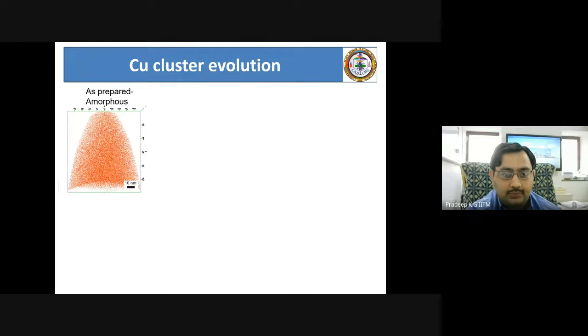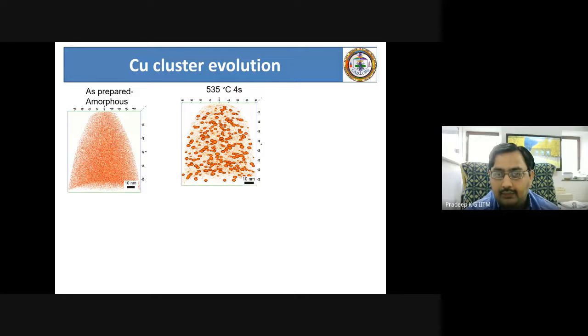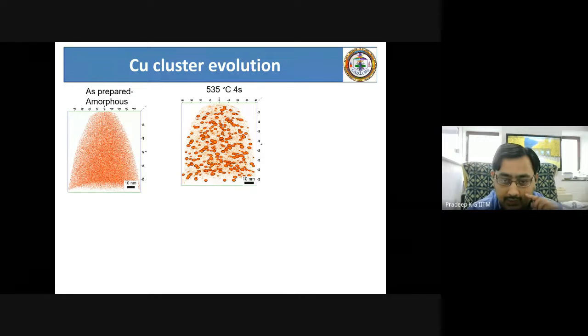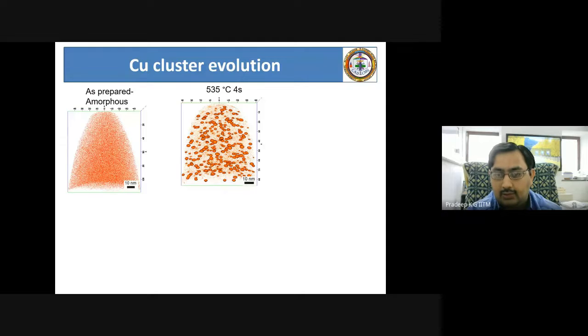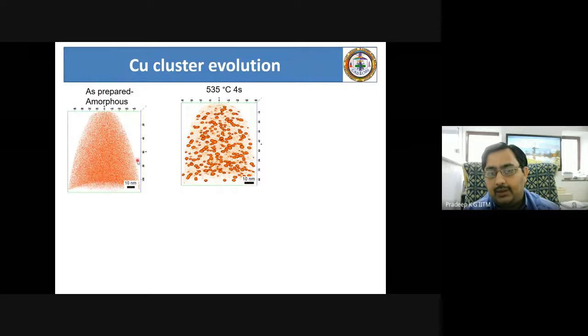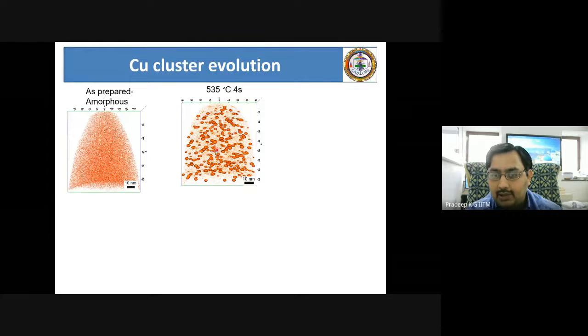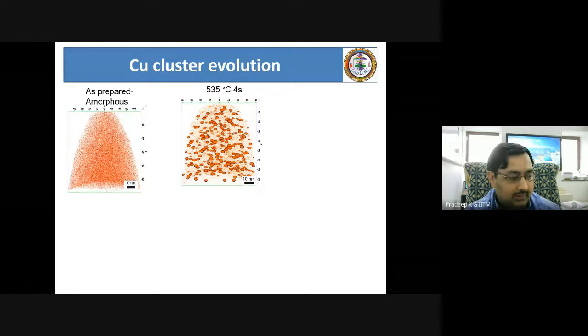You can see in an atom probe, in an as prepared state, all the copper atoms are homogeneously distributed in a 3-dimensional volume. At 535 degrees, where X-ray diffraction and transmission electron microscope said everything is amorphous, you can see a large volume fraction of clusters of copper that has emerged from a randomly distributed copper matrix. That means all these individual atoms of copper started coming together and formed these nanoscale clusters throughout the 3-dimensional volume.